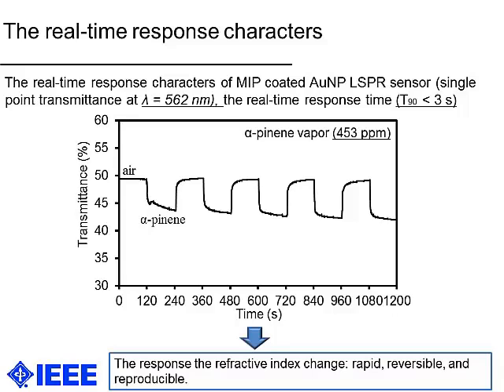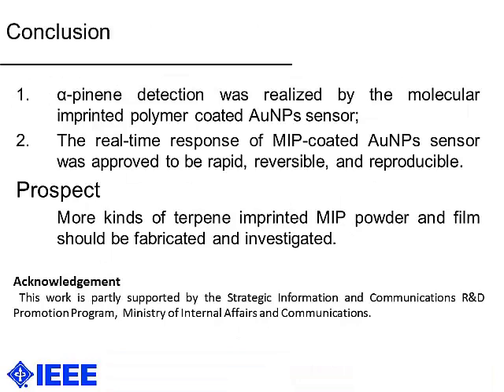The real-time response was detected as a single point transmittance at lambda equals 562 nanometers, and the real-time response time T90 here is less than 3 seconds. And here the response to the refractive index change is rapid, reversible, and reproducible. Even though there is a MIP layer on the Au nanoparticles, there is not much effect on the sensing speed. And then the conclusion part will be, firstly, alpha-pinene detection was realized by the molecular imprinted polymer-coated Au nanoparticle sensors. Secondly, the real-time response of MIP-coated Au nanoparticle sensors was proved to be rapid, reversible, and reproducible.